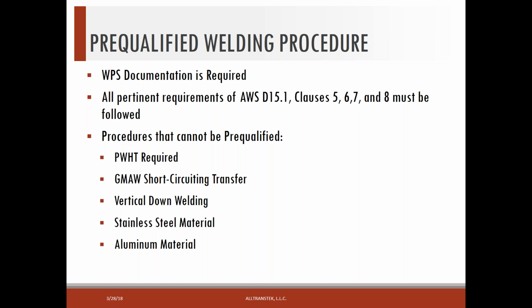Some procedures that cannot be pre-qualified are if we're going to have post-weld heat treat, if we have gas metal arc welding with a short circuiting transfer, or if we're welding vertical down. And in D15.1, stainless steel material and aluminum material cannot be pre-qualified. We have to develop a qualified welding procedure for those materials.